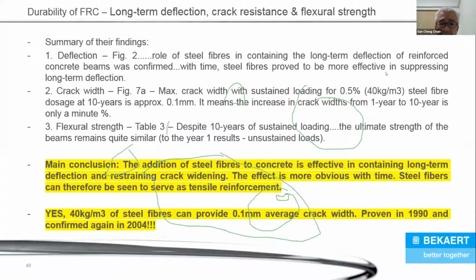The main conclusion: the addition of steel fibers to concrete is effective in containing long-term deflection and restraining crack widening. The effect is more obvious with time. Steel fibers can therefore be seen to serve as tensile reinforcement. So 40 kilograms of steel fibers can provide 0.1 millimeter average crack width. This is proven in 1990, confirmed again in 2004.